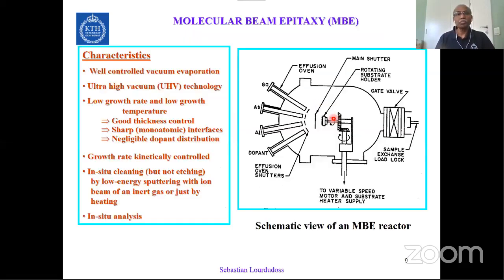And we have yet another technique called molecular beam epitaxy. Basically, it is the toy of the physicists because they could grow very low dimensional structures in the beginning. It is a completely ultra high vacuum technology. You have to have very high vacuum, and you have the sources placed in the effusion cells. When you heat the effusion cells and open the shutter, the molecular beam will evaporate and just strike the wafer here, and all will react.